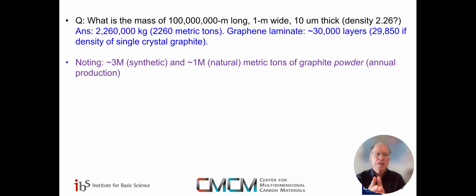Okay, so what's the mass of a 100 million meter long, 1 meter wide, so 100,000 kilometers, 10 micron thick, density the same for HBN and stacked graphene, density of graphite? Well, the answer is it's 2,260 metric tons. And if that were a laminate of graphene, or HBN, it would have about 30,000 layers. And if we use the density of single crystal graphite, we can get a particular number. So currently in the world, we manufacture roughly 3 million metric tons of synthetic, and we mine 1 million metric tons of natural graphite powder.